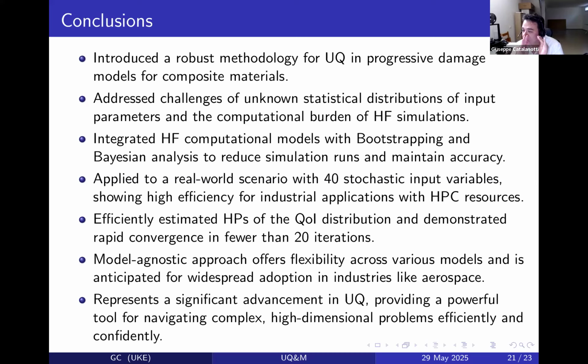Apart from that, even if you have good data, there is another issue. When you sample from data, this data will come probably from the center of your distribution. So with this approach, you actually can lose some information about details of your distribution. But this is something you can take into account, because you can combine this with other approaches. For example, in assuming the functional form of the quantity of interest, you may assume several, right? And therefore take the one that is most conservative.